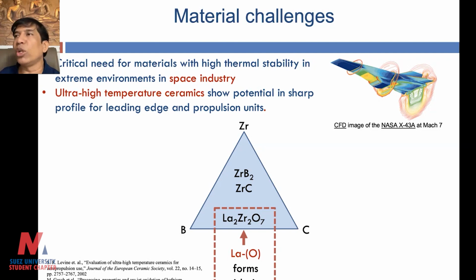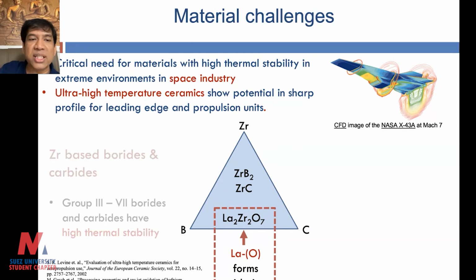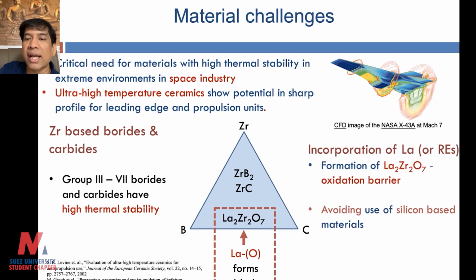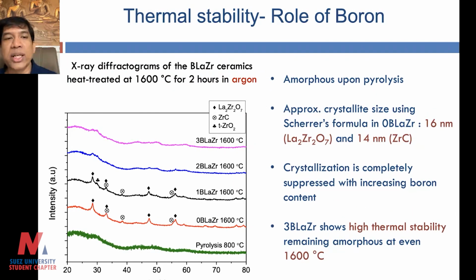In this specific case, I'm showing you borides and carbides of zirconium, but we can also extend it to hafnium carbide, hafnium boride, tantalum carbide, tantalum boride, and so on, all of which have high temperature stability beyond 2500 degrees Celsius. So we have been working on this for quite some time, for nearly 2 years, and we have done some basic studies.